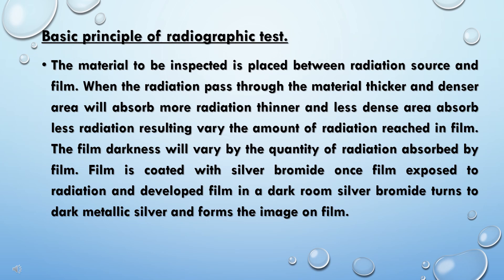The basic principle of radiographic testing: the material to be inspected is placed between the radiation source and the film. When radiation passes through the material, thicker and denser areas will absorb more radiation, while thin and less dense areas absorb less radiation.